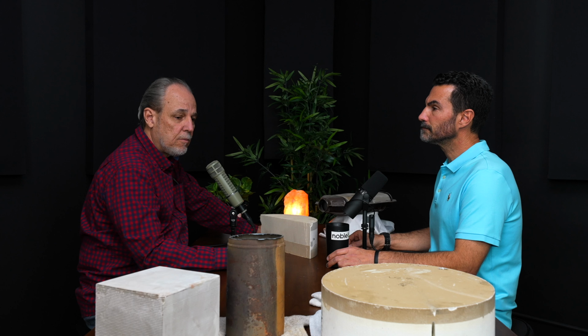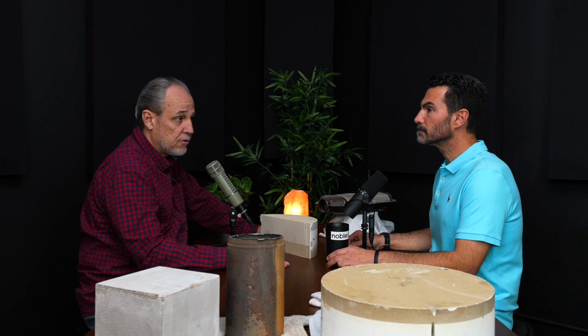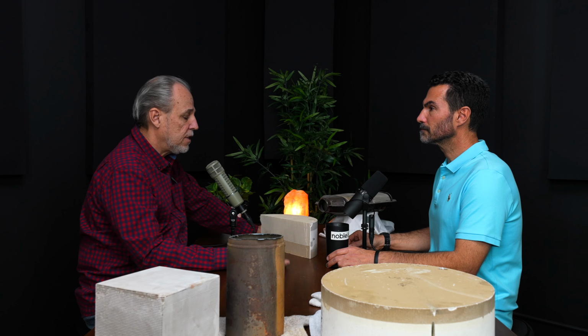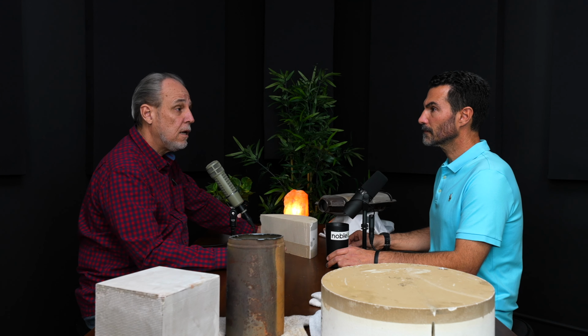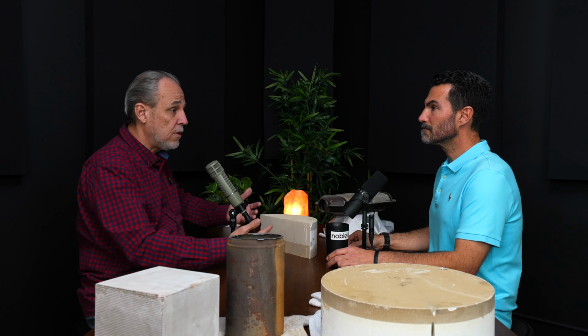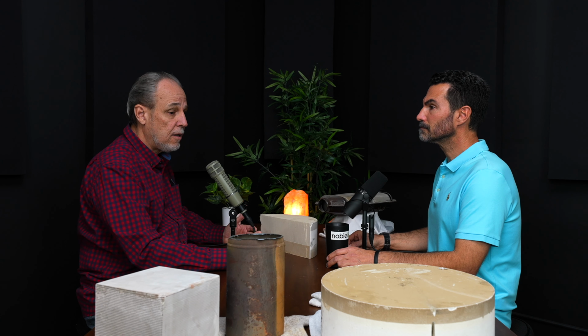Silicon carbide melts at a higher temperature. It is very difficult to recover the precious metals from the silicon carbide in the furnace. Now, why is that? Well, silicon carbide is a material that's used in many different industries. They use it to create abrasive grinding wheels, cutoff wheels. It's very stable at high temperature. It's used to manufacture crucibles for melting metal. So a pot furnace, maybe a gas-fired furnace, would have a silicon carbide crucible in there that would contain the molten metal. Maybe it's copper, silver, gold, high temperature melting, around 2,000 degrees Fahrenheit, up to about 2,500 degrees Fahrenheit. Those crucibles will withstand that temperature.